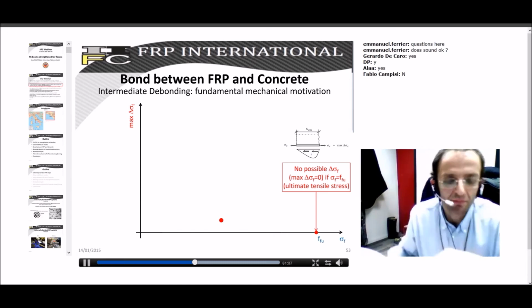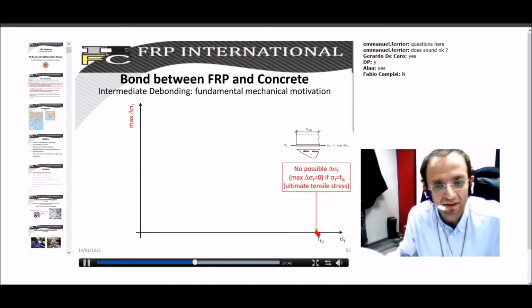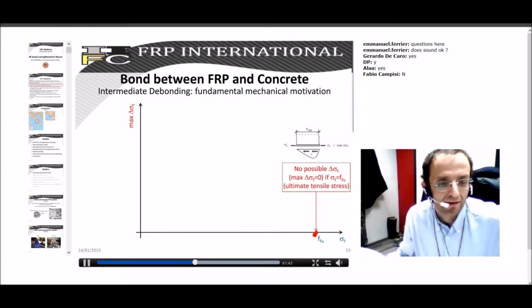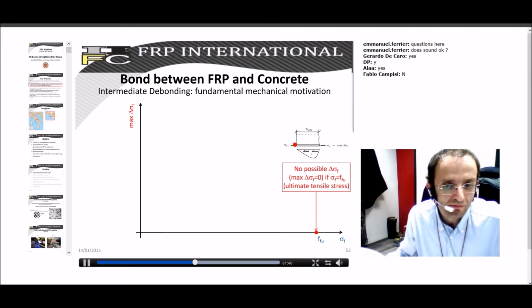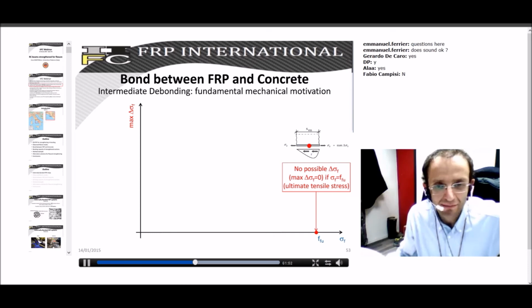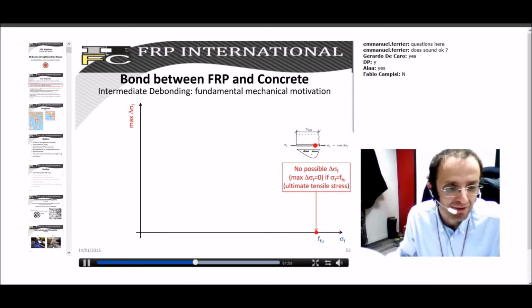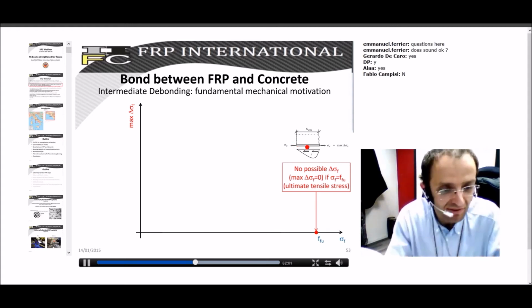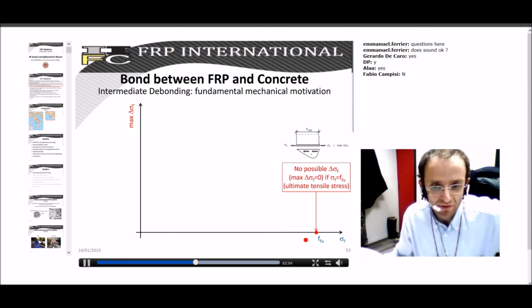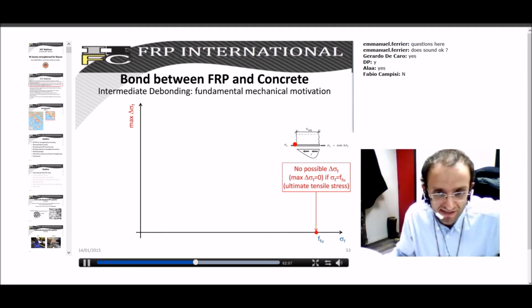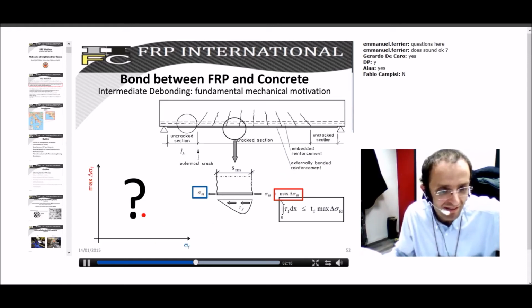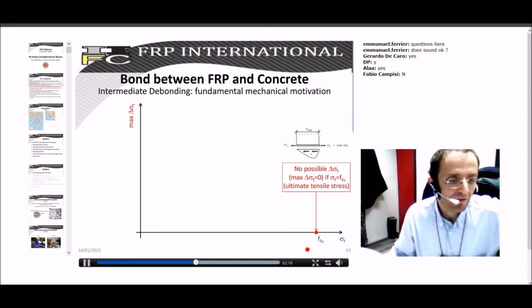For instance, let's start from the first limit case. Let's suppose that sigma f is equal to the maximum strength for the composite strip. Here, for some reason, you have attained the maximum strength of the composite strip. How much would be the delta sigma? Of course, you can have no delta sigma, because any delta sigma, even an infinitesimal one, will result in the tearing, in the axial rupture of the FRP. So this means that if you start with sigma f equal to f_fu, the delta sigma is 0. So this is one of the possible points of this mysterious relationship between sigma f and maximum delta sigma. So this is for sure one first point.